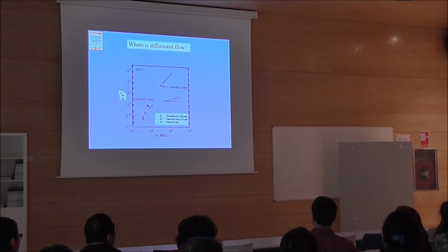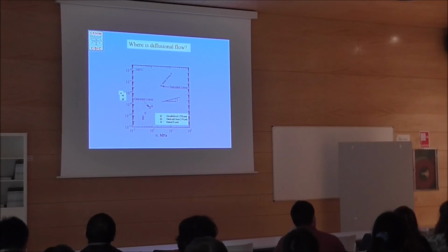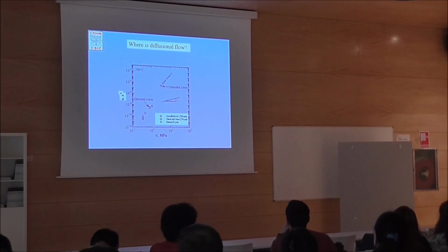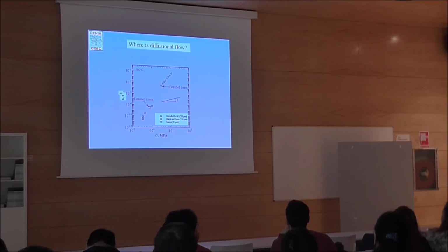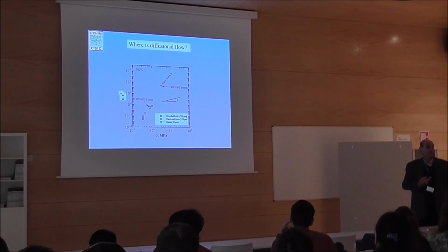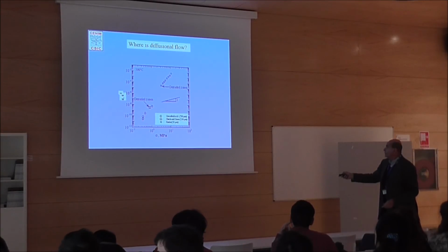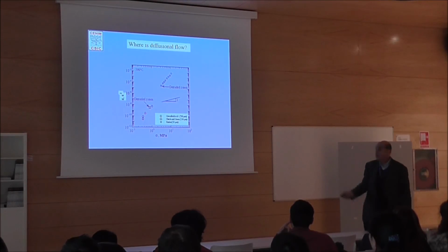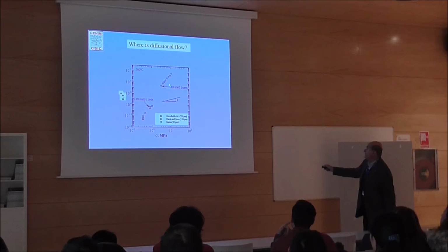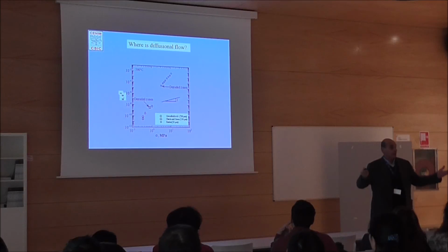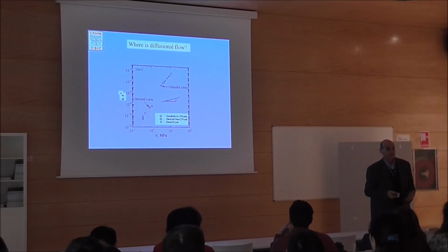So we introduced the squares and the additional flow and so on. We went into the same material, and then we looked at the microstructure, and we discovered not our results, their results. We discovered the denuded zones here, and this is n equal 4. And we discovered the denuded zones here. This is 500 degrees Celsius. The denuded zones there. What's going on? I mean, you have to have n equal 1. It's the diffusion flow, n equal 1. So the first question.